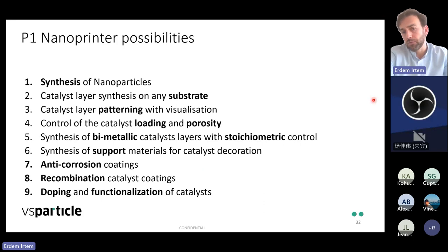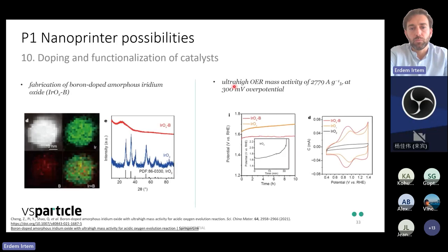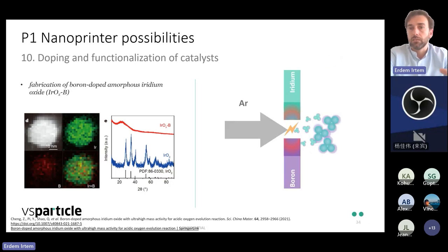Another application that I find could be interesting is doping and functionalization. I was checking this article where they doped iridium oxide with boron, for example, and they have shown that it has a higher stability versus the undoped version. They attributed this to creating some active sites, but also lowering the electrical resistance. So I was thinking it could be possible by just playing with the ablation rate and then doping boron at a rate that you would like to have.